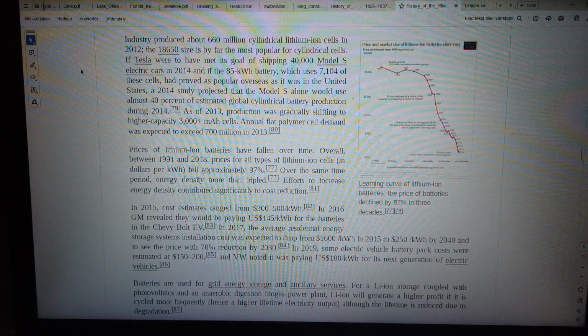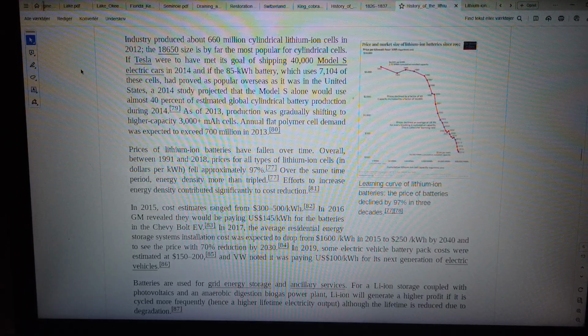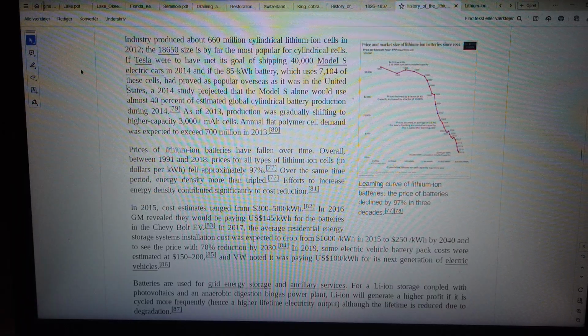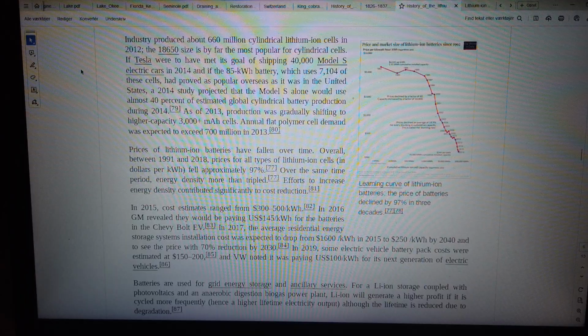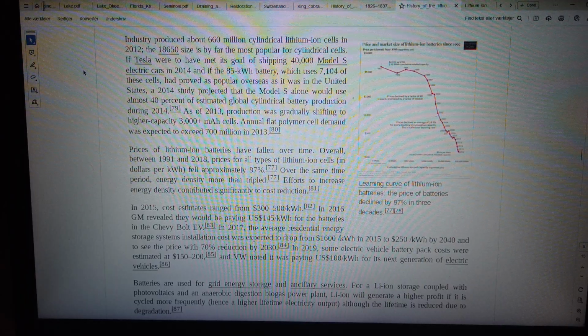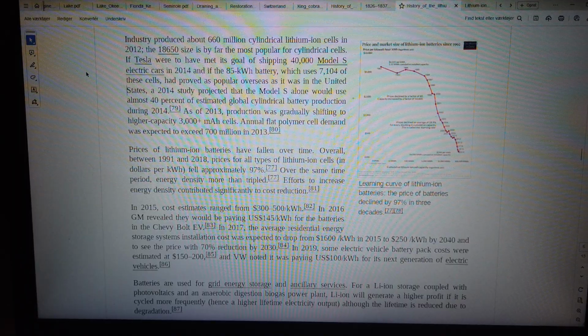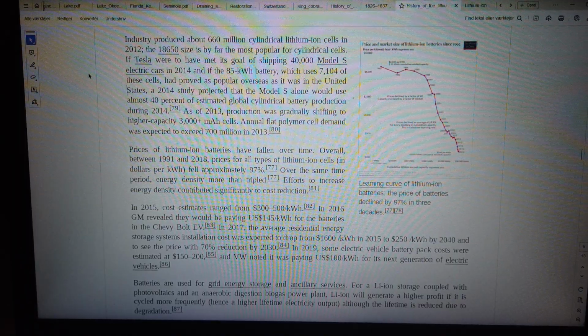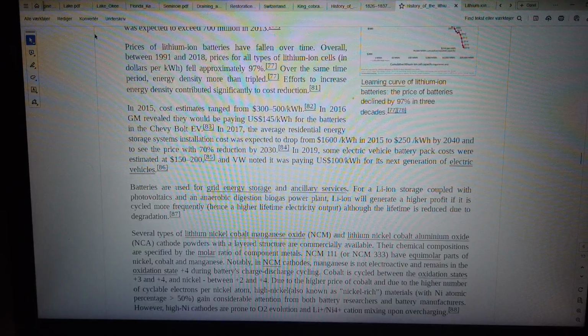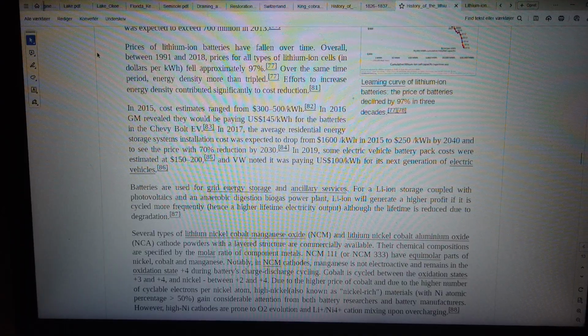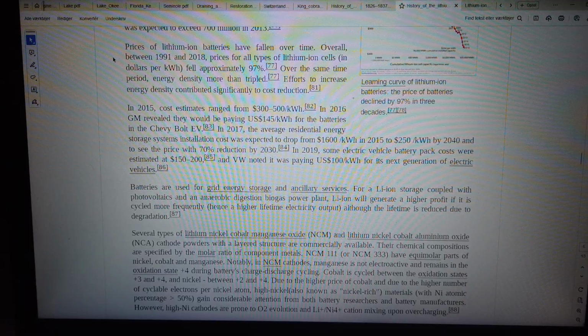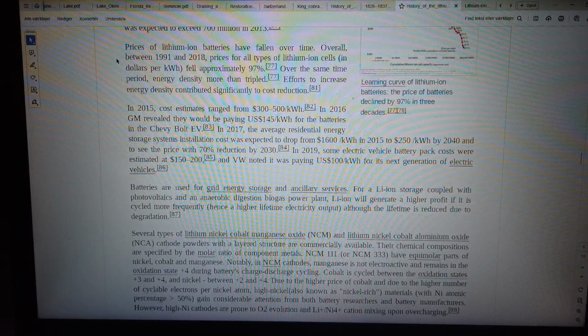79. As of 2013, production was gradually shifting to higher capacity 3,000-plus mAh cells. Annual flat polymer cell demand was expected to exceed 700 million in 2013. 80. Prices of lithium-ion batteries have fallen over time. Overall, between 1991 and 2018, prices for all types of lithium-ion cells, in dollars per kilowatt-hour, fell approximately 97%. 77. Over the same time period, energy density more than tripled. 77. Efforts to increase energy density contributed significantly to cost reduction.